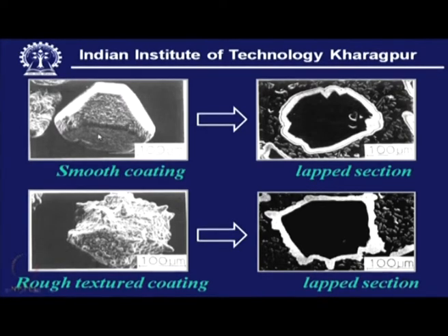bond. So, here mechanical anchorage is more important, and if we have a careful look we can see the spikes, and these spikes actually act like a good mechanical anchor, and this resin bond has a firm grip on this surface. As a result, we expect longer life of this grain within the bond, and there is hardly any premature dislodgement of the grain.